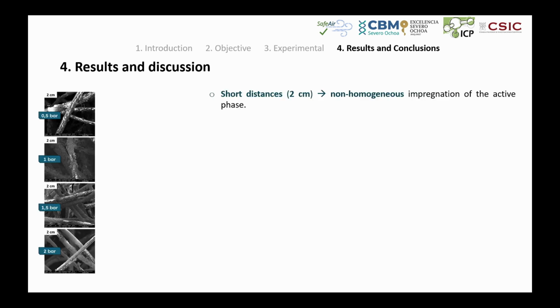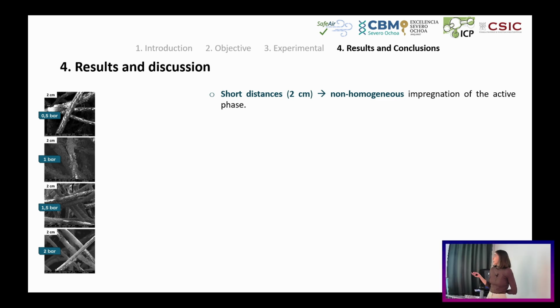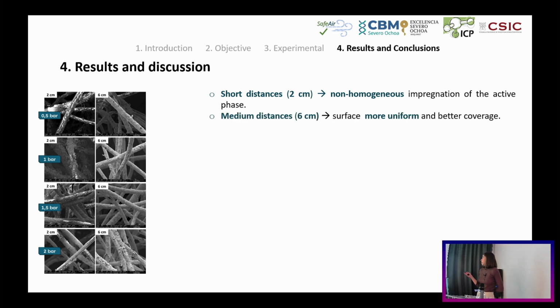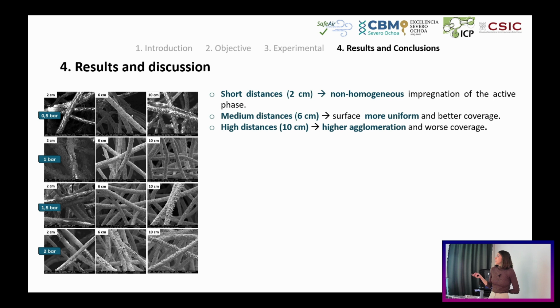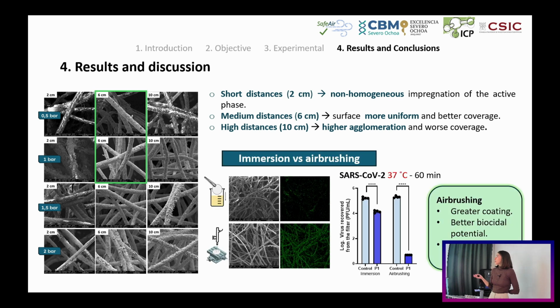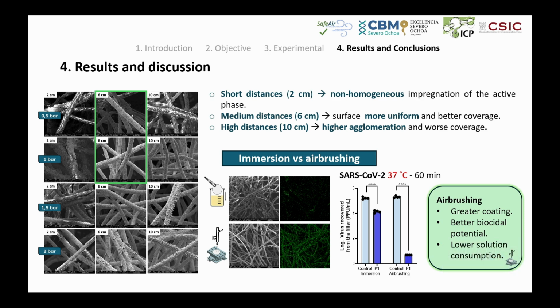Here I show some micrographs where we can observe that at short distances the impregnation of the active phase is non-homogeneous, but if we increase this distance the surface is more uniform and there is a better coverage. However, at high distances the impregnation leads to a high agglomeration and worse coverage. So for this reason we select the filters prepared at medium distances and lower pressure to compare with the conventional method of immersion. We can conclude that the airbrushing method shows a greater coating with a better biocidal potential.